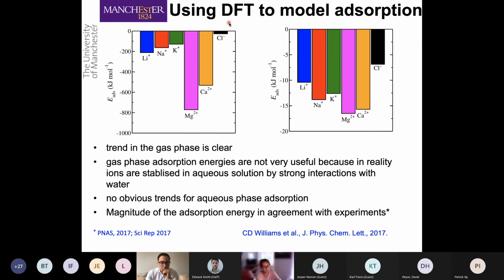So we did some calculations ourselves because we were very interested to see what happens and why these ions are absorbed or not. And we initially started with DFT calculations. So if you perform a DFT calculation of, for example, a flake of graphene with an ion on top of the graphene, and then you calculate the absorption energy as the difference in energy between when the ion is far away from the surface and when it's absorbed, you obtain negative absorption energy, meaning that the ions are absorbed, but these are very huge numbers. You have the trend that you expect, so smaller ions absorb less, the larger ions absorb the most, and divalent absorb more than monovalent ions.